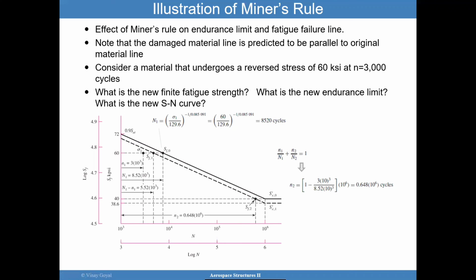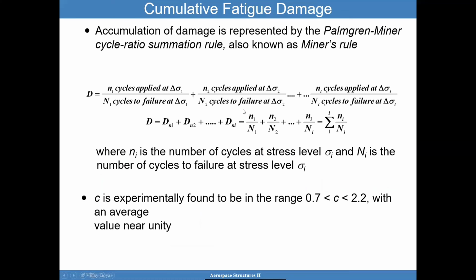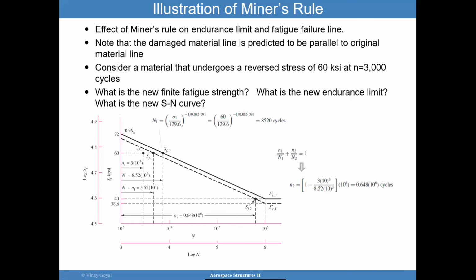I can solve for N2, assuming that capital N2 is 10 to the 6 cycles, because I want to figure out how this point gets impacted. And when I do that, I get an n2 of 648,000 cycles. That corresponds to a line all the way up to here. So you can then draw that point. The idea here is you're trying to determine that knockdown factor due to consuming some of that life. Again, you don't have to do this. We can use this approach very readily to figure out the cumulative damage, but this is just another approach to figure out what is happening physically.